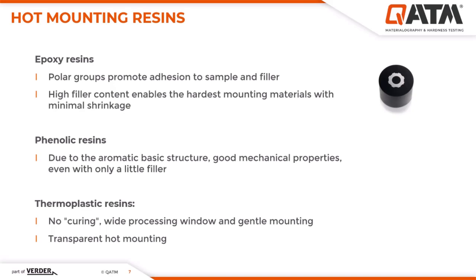Epoxy resins offer very good adhesion to the sample itself and to the fillers contained in the resin, resulting in a minimal gap between the mounting material and the sample. Due to their high filler content, epoxy resins also achieve a high hardness, making them well suited for mounting hard materials as well as for subsequent grinding and polishing.